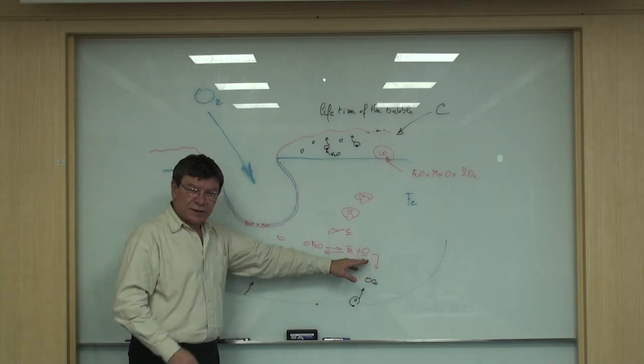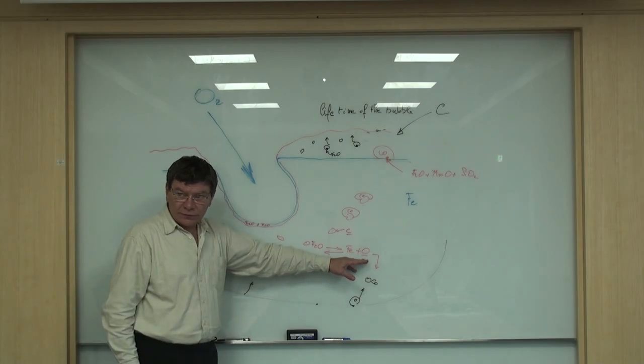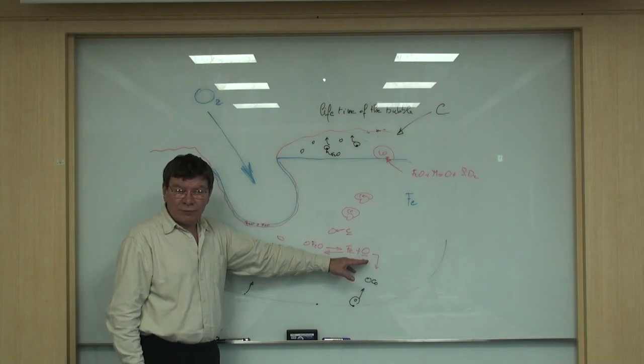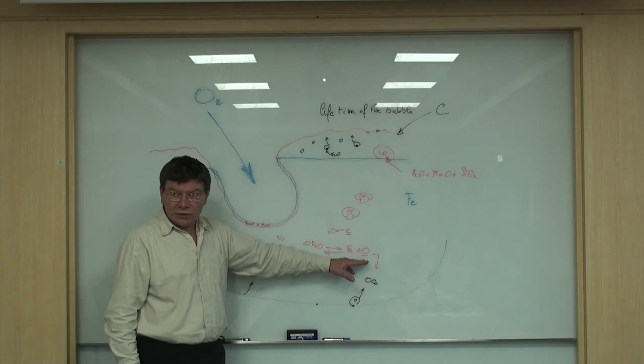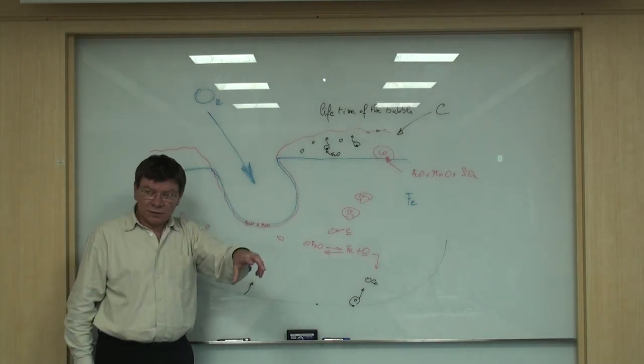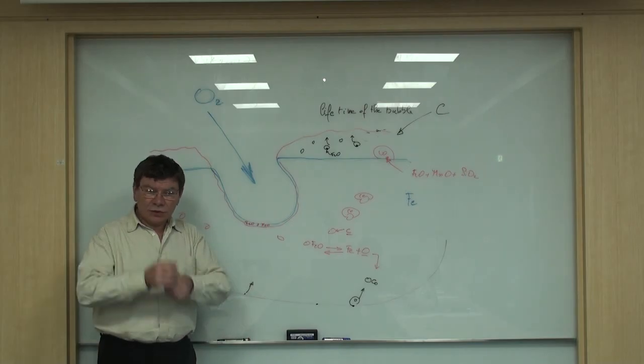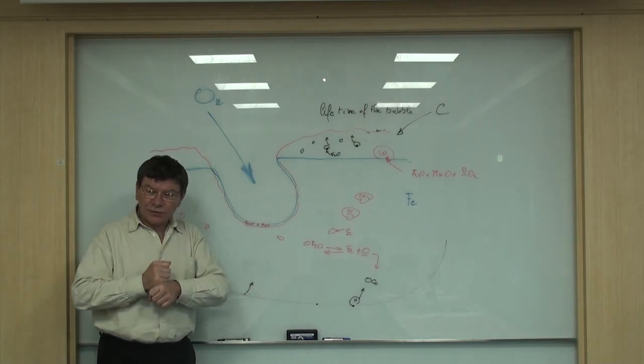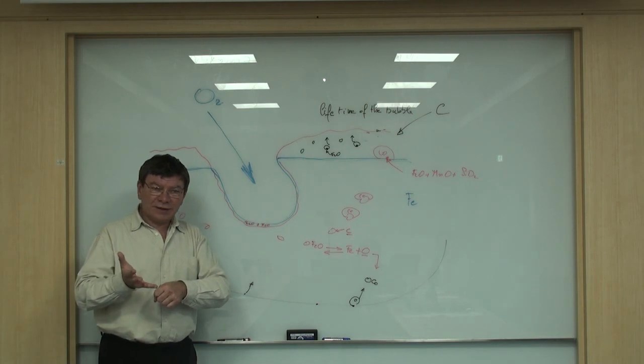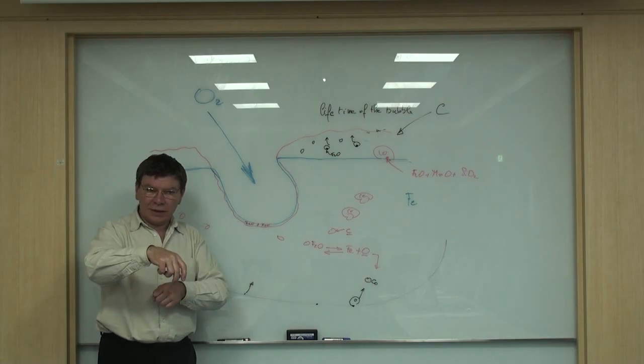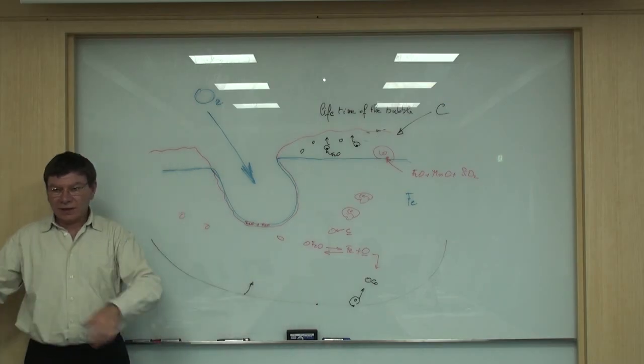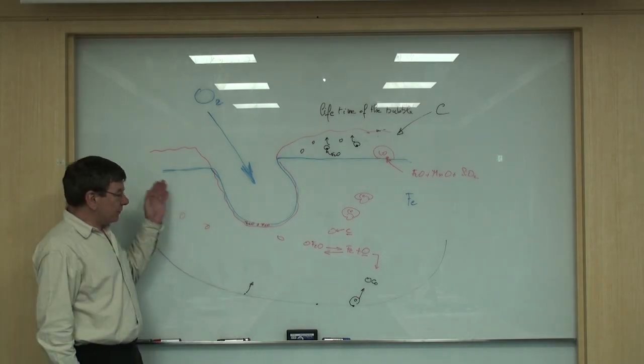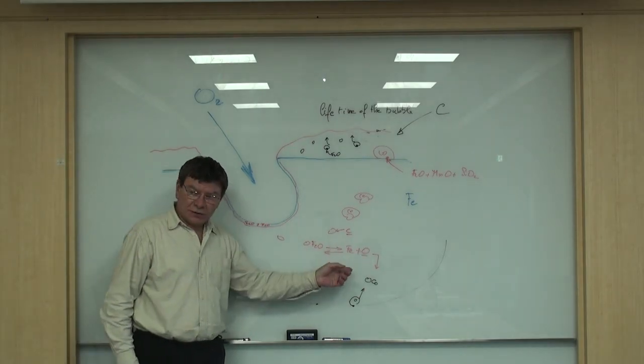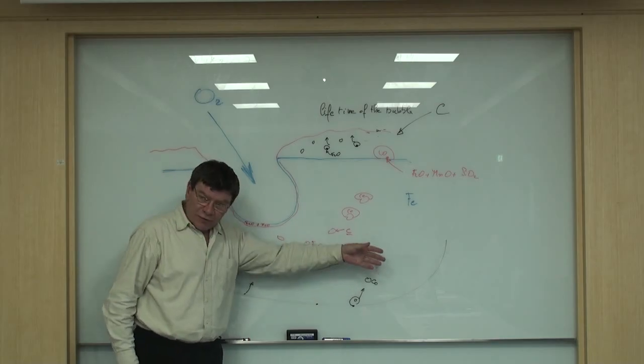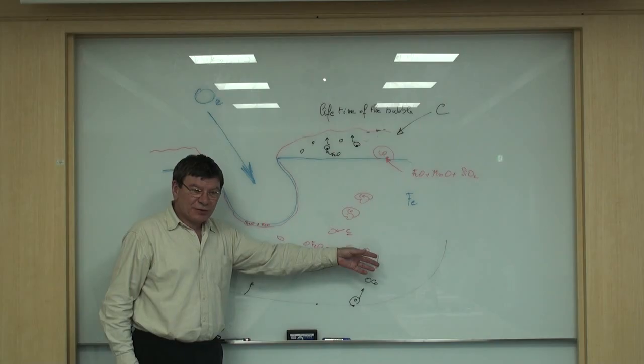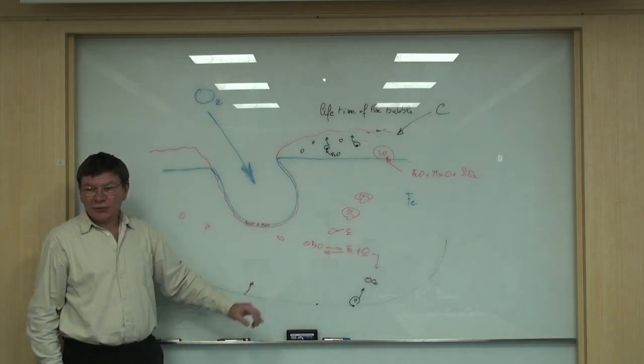The oxygen is not necessarily at the equilibrium. That's why you may have big boiling from time to time. Because imagine you don't have an arc, so the bath is not moving so much. You inject a lot of oxygen because you are away from the target. And then you start with the electrodes to reheat the furnace, and then you get big boiling, all the slag and some steel on the furnace platform. Why? Because you are away from the equilibrium here. Oxygen solubility is overpassed. So you have to take care when you inject oxygen to do it carefully.